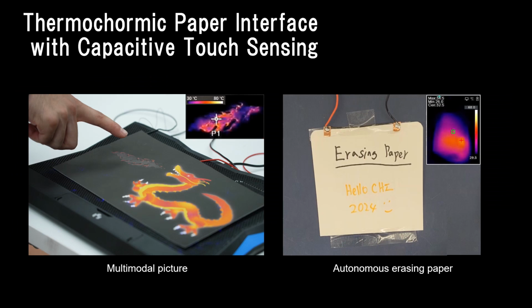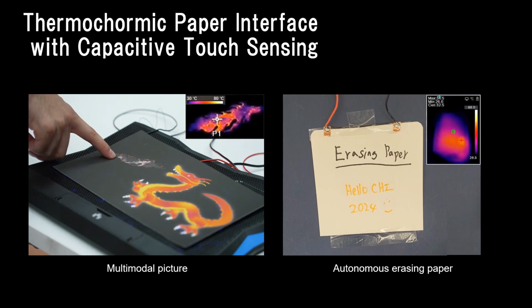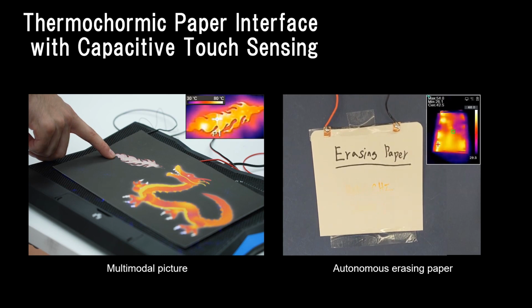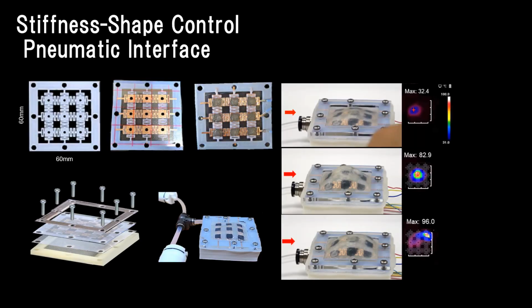We also found capacitive touch sensing ability of the conductive carbon nanomaterial heater. By integrating thermochromic ink, we can create interactive thermal paper interface, such as multimodal picture and autonomous erasing paper. Carbon nanomaterial heater can also be used to control the shape of the pneumatic interface by controlling the stiffness of the 3D printed mesh exoskeleton.